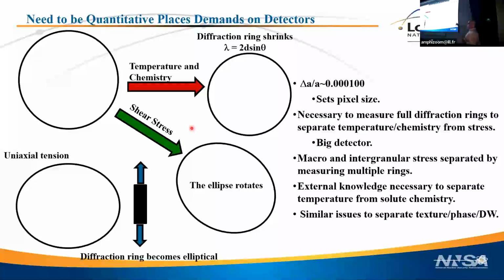Usually to separate temperature and chemistry, which both just change the radius of the ring, you have to have some extra knowledge. For instance, I can have a thermocouple on my sample, and that'll tell me the temperature. Or quite often what I like to do, because I don't trust thermocouples because they're often removed from your sample a little bit, I like to put the sample, say, in a can of something else. Like if I'm measuring titanium, I put it in a steel can, and then I measure the lattice parameter of the can, and that tells me the temperature of the can. And I get that measurement for free. So if I have an extra piece of knowledge, then I can separate temperature from chemistry.